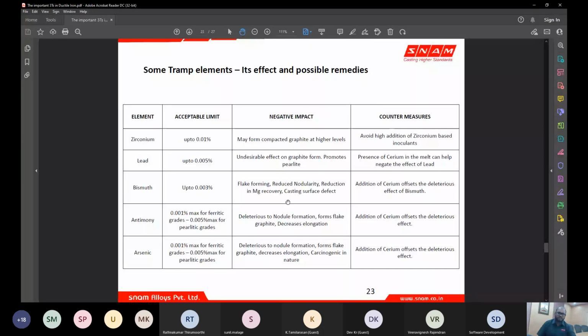It is because when these two combination elements keep increasing, it is again going to build up in your liquid metal and it can have a negative effect also. So as we say, too much of anything is good for nothing. The same way, too much of nodulizer is not good for your ductile iron. Too much of inoculation is not good for your ductile iron. The same way, too much of trace elements, too much of cerium is not good for ductile iron. So it is to be arrested at the source itself rather than taking a countermeasure.